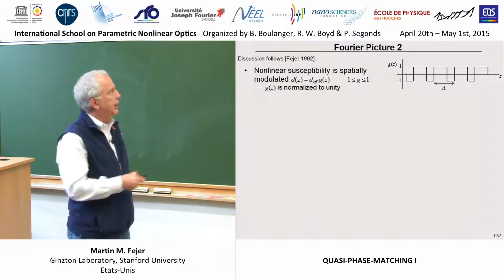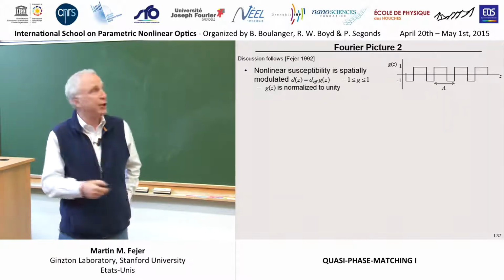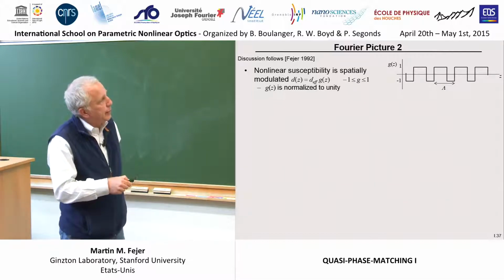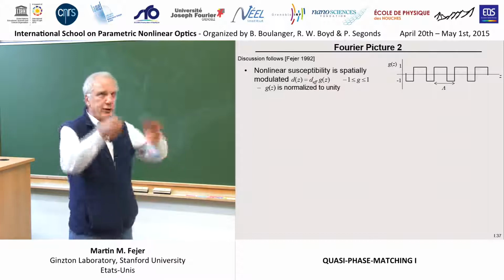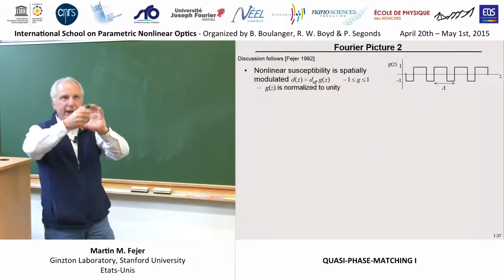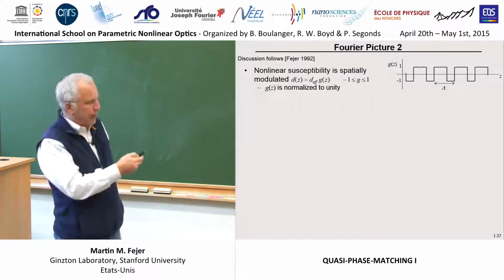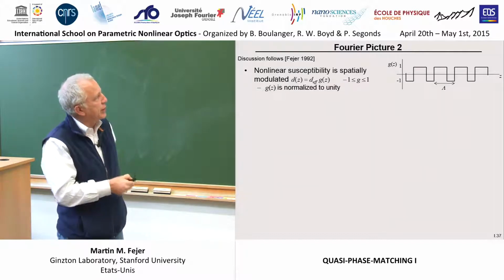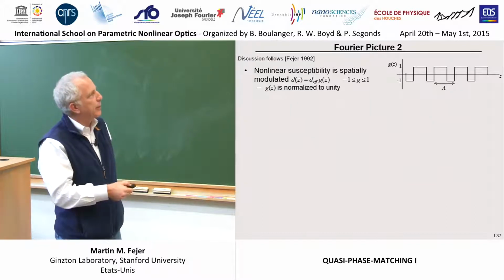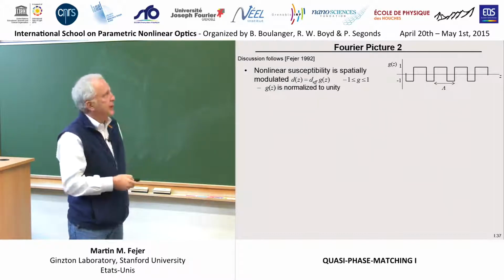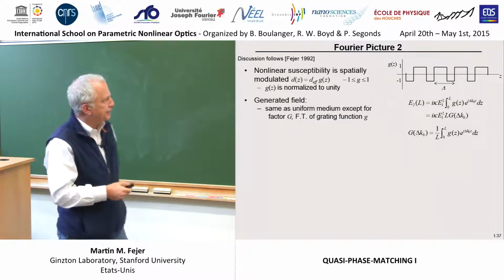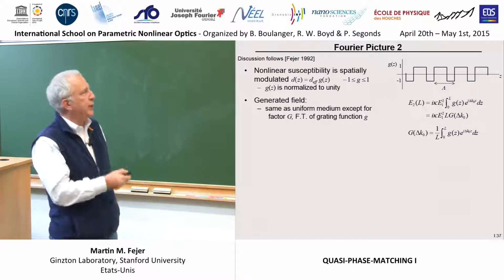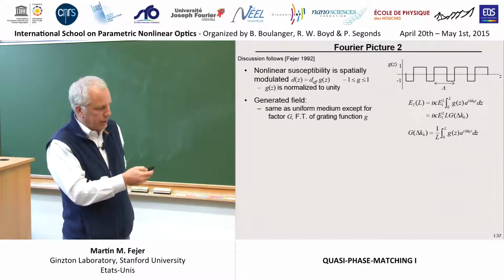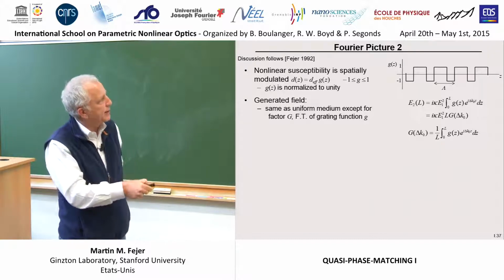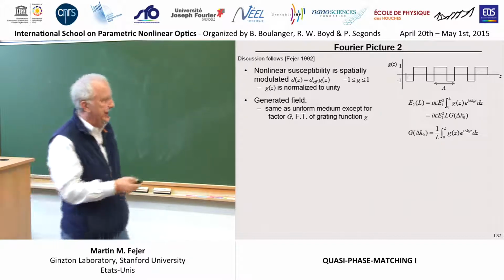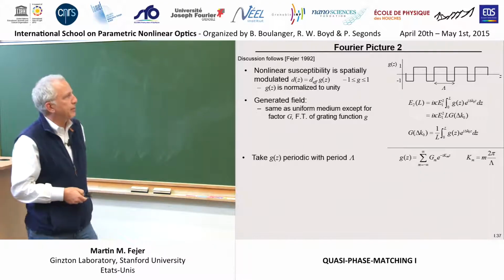Let's imagine that, as most of our quasi-phase matching media behave, there's only two choices. You can have plus or minus d effective as you go from an up to a down domain. You don't have a continuous range of values in between. So we can describe our modulated nonlinear coefficient by some function g that goes between -1 and 1 with some period lambda, the sum of the up and down domain lengths. We just said that our generated field will go like the Fourier transform of this thing, so it will just go like the integral of this function. We'll call that capital G in the Fourier transform domain.